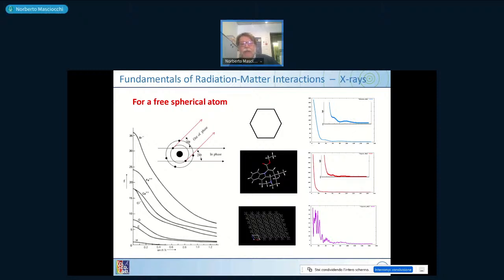If you take another organic molecule, this is a drug called vinpocetine, and you compute what the scattering should be, again you have a very fast decaying plot. Possibly you see a small bump here, which is illustrated in the insert, and the second one at higher angle, but again, it's very poorly informative plot. So the reason for this is that these are molecules in gas phase.